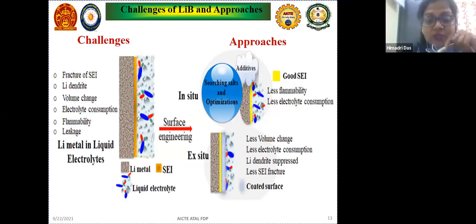So we can go for a surface engineering process. Researchers are searching for compatible salts, or we can say additives actually. With these additives, one may prepare a good solid electrolyte, which can reduce the flammability as well as electrolyte consumption. When we go for developing an artificial solid electrolyte interface, or when we reduce the fracture in the solid electrolyte, it can definitely suppress the dendrite formation, and also reduce the electrolyte consumption or volume change in the electrode.